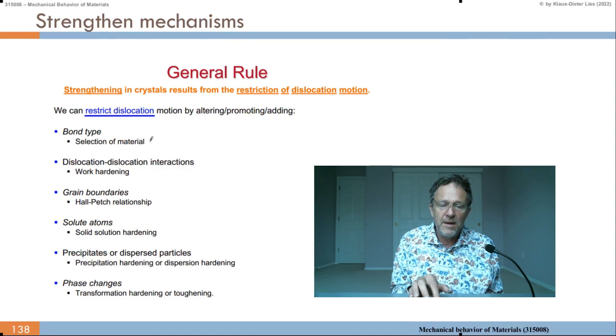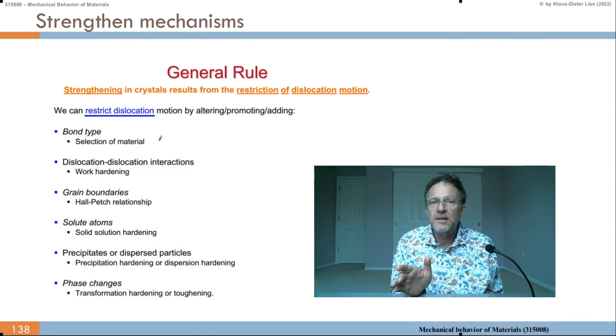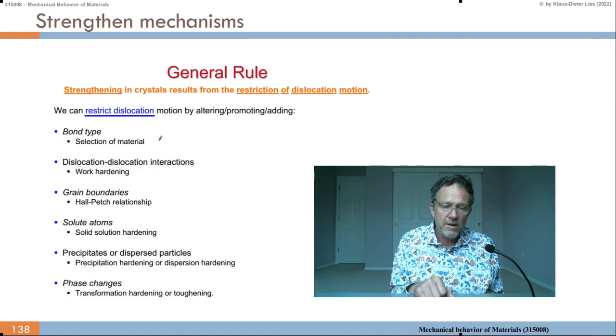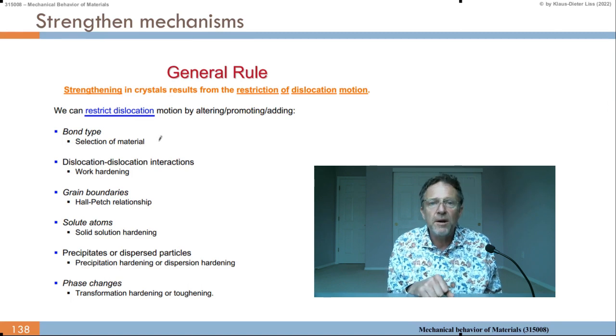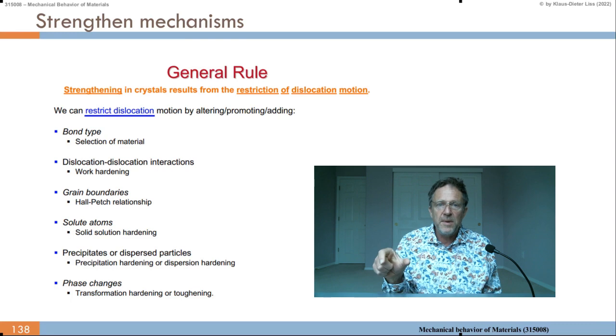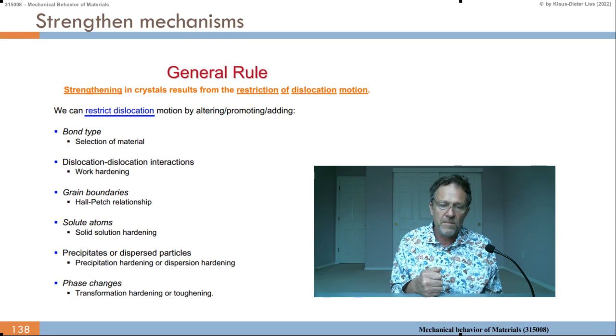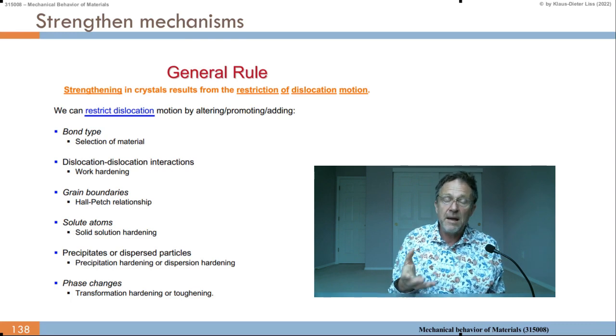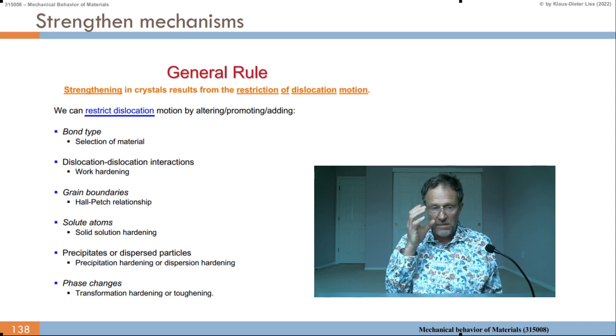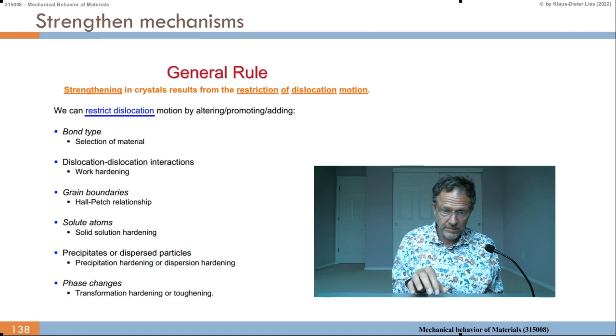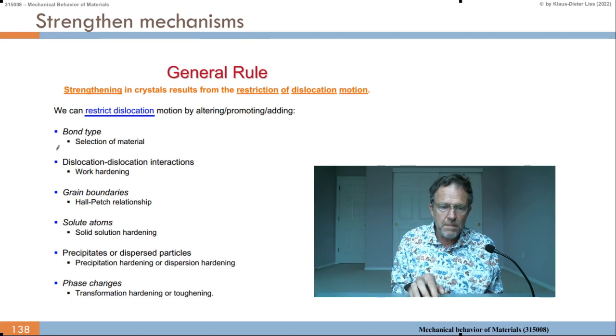Yeah, if we have an FCC lattice, aluminium, and then we say, okay, we take now titanium aluminium, then we have titanium aluminium intermetallic bonds, and they make the material stronger than pure aluminium. So you select the bond type. Then we have the dislocation interaction. This is the work hardening I mentioned already.